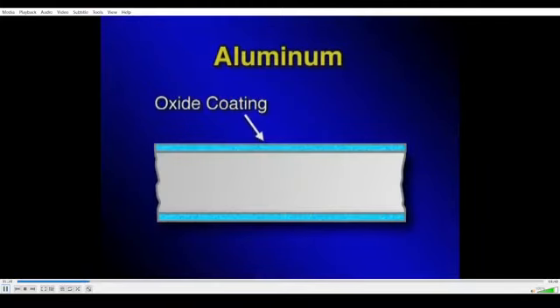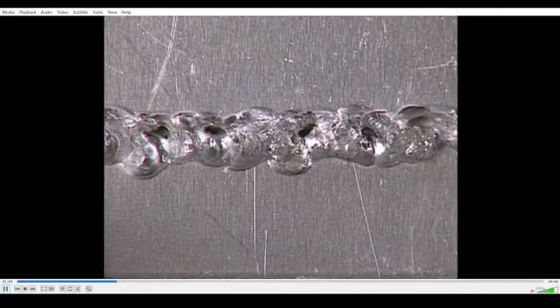As soon as it's exposed to oxygen in the air, it forms a protective oxide coating hundreds of times thinner than a human hair. This oxide coating gives aluminum its corrosion resistance. It also makes it hard to weld. For one thing, even though aluminum oxide is next in hardness to diamond, it's quite porous and can retain moisture and other contaminants. These break down in the heat of the arc to form hydrogen gas, and hydrogen is extremely soluble in molten aluminum. So you have to make sure that the surface of the metal is free of moisture, oil, and grease, or you could end up with porosity in your weld.